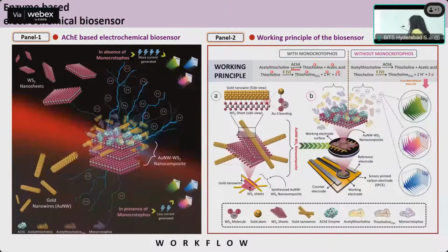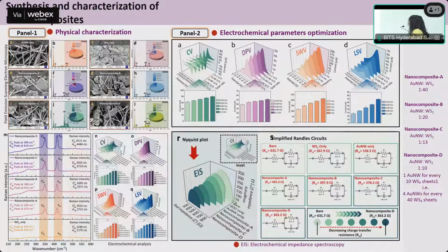percent RSD. Now this is the electrochemical sensor for the enzyme based sensing. So what he has done, he has used WS2 nanosheets and the gold nanowires in this case and made the immobilization of the AChE enzyme and tested the presence of monocrotophos. So, coming to the characterization, he has done various combinations. So, this is only the gold nanowires, and this is the WS2 nanosheets, which is conductive in nature, and that's the EDAX, which shows the characteristic elemental peaks.